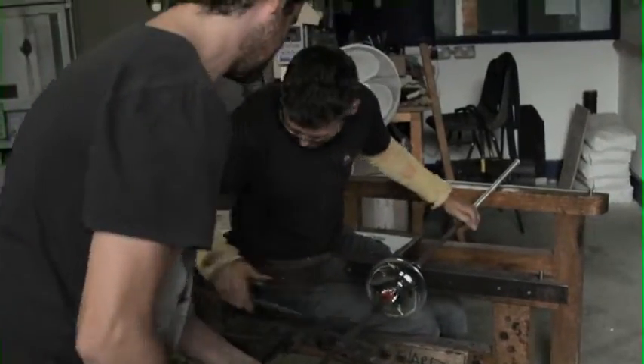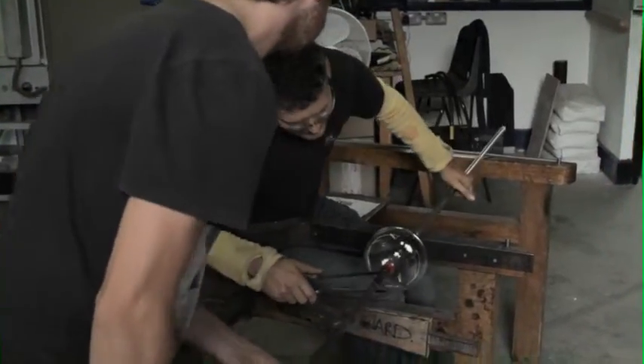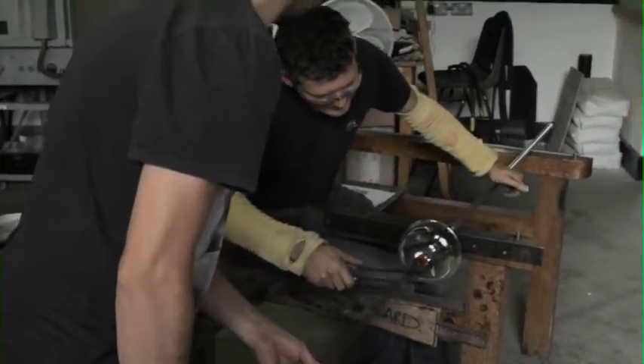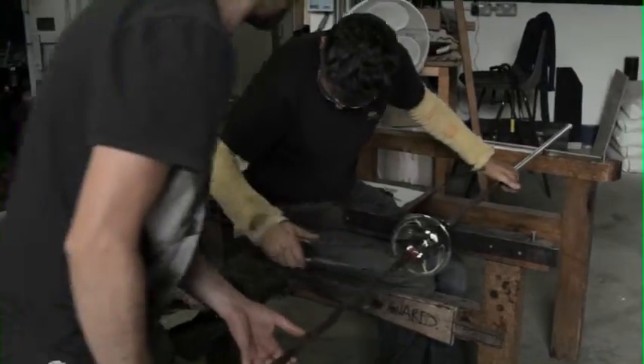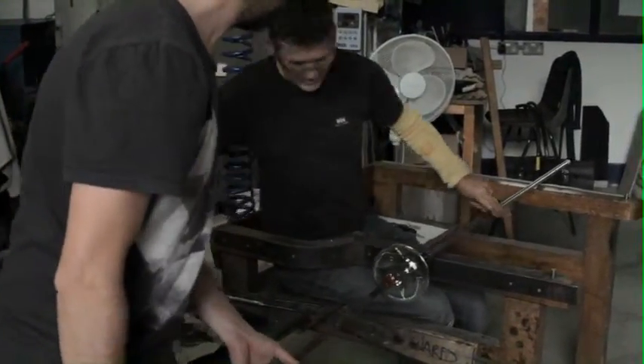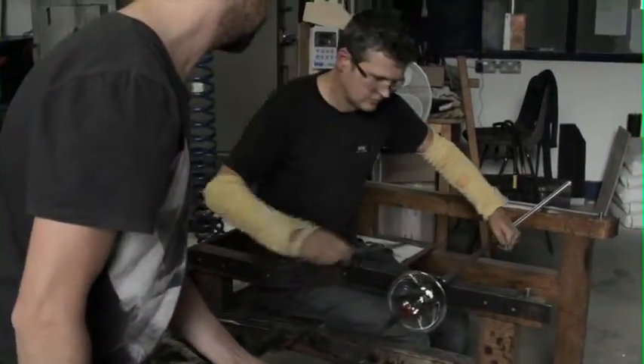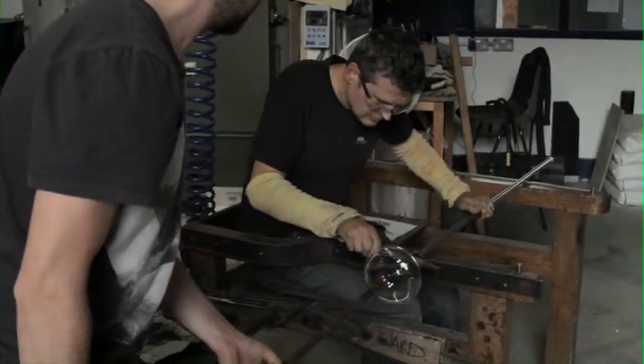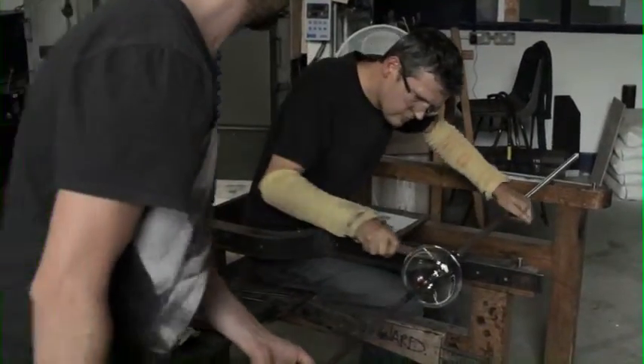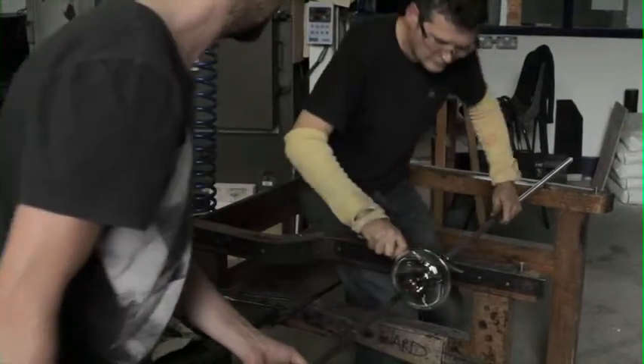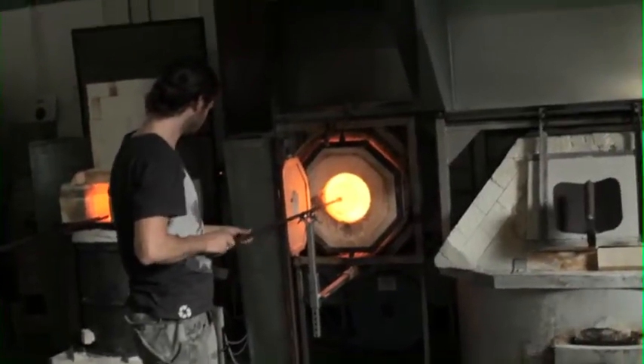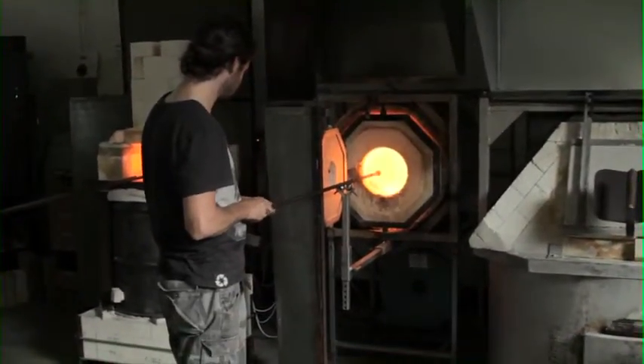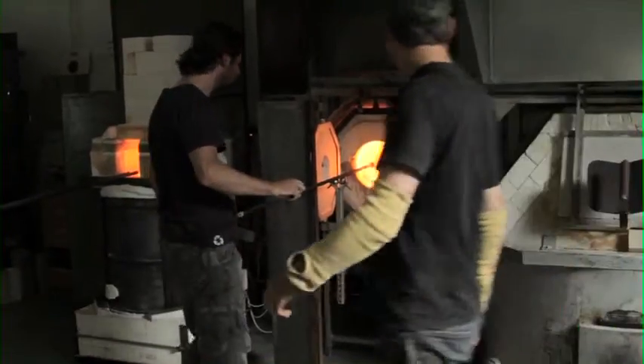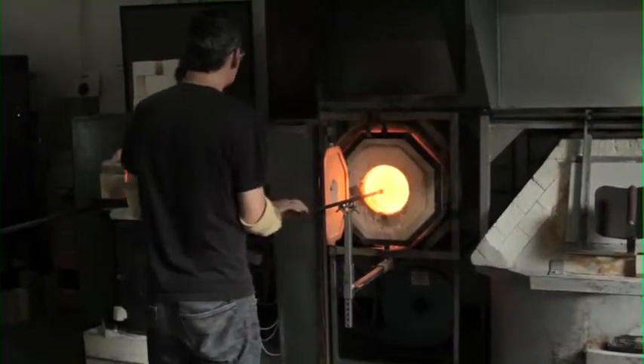Sarah couldn't melt large amounts of glass at Imperial College. She had to pour the glass onto a metal plate, which resulted in small round pellets that had to be ground and polished to produce the completely flat surface needed for surface analysis techniques. Of course, a cold finished surface removes the skin of the glass, which isn't comparable to a blown glass finish. Also, it's extremely difficult to refine glass in small crucibles, even at temperatures reaching 1400 degrees C. What she needed were large, thin, blown plates.